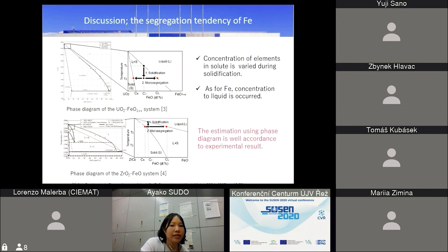And the microsegregation of Fe to the liquid occurs. During solidification, this microsegregation is repeated. And finally, the macrosegregation of iron to the residual melt inner region occurs. This is the ZrO2-FeO system phase diagram, and the tendency of segregation of iron is similar to the UO2-FeO system. This estimation using phase diagrams is in good accordance with the experimental result.